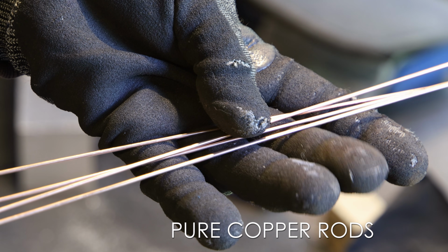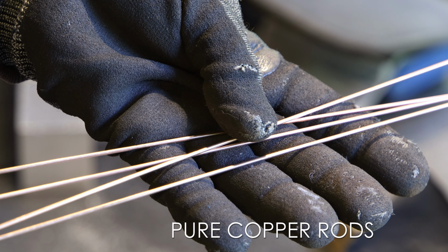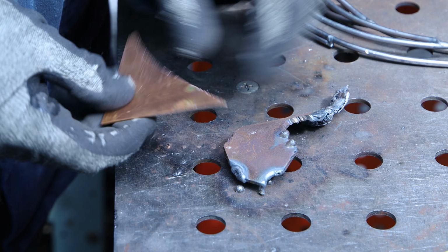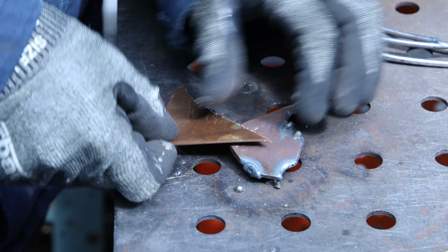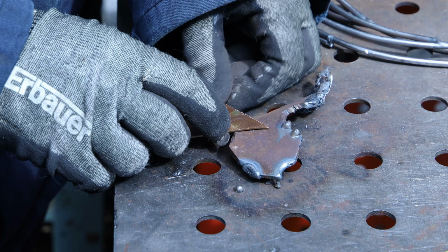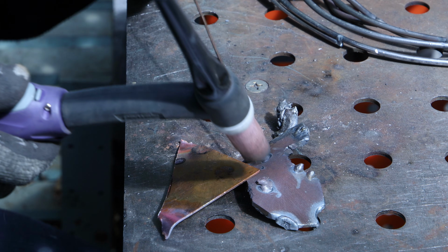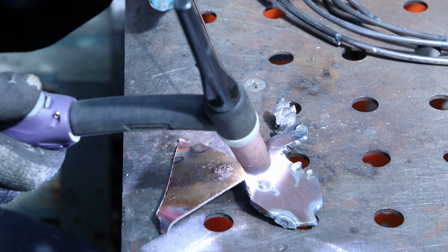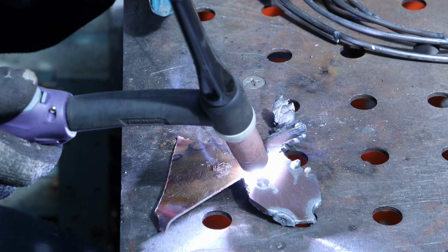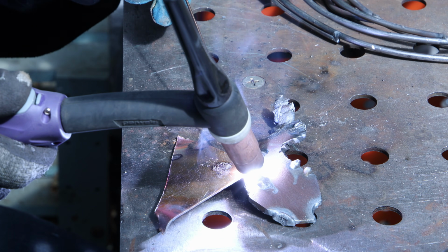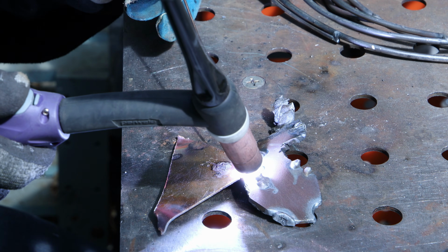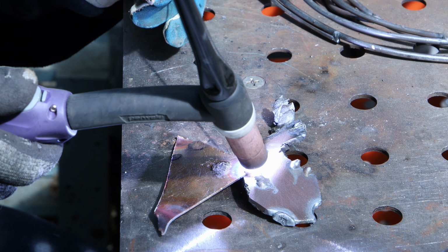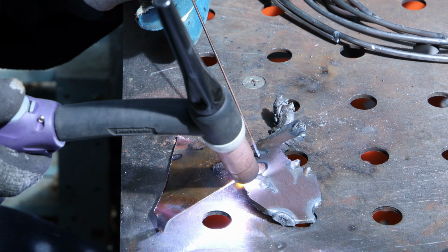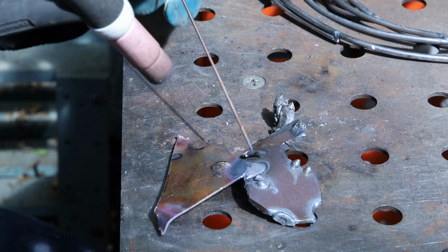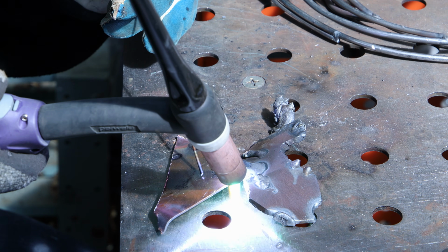Now TIGging thin sheet of copper is not easy. I took some leftover pieces of copper and some steel, just to show you how tricky it is, because copper will work as a heat sink, so you need to feed it with lots of heat, but by the time you do that, the edges of the copper will melt. So I need to very quickly bring in the rods, almost too quickly, which is going to leave me with some very unpretty welds.